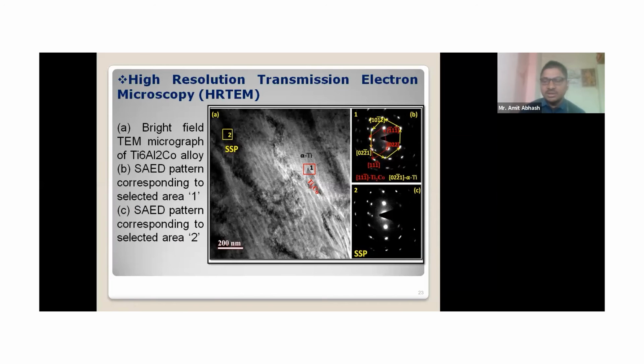So by going through the transmission HRTEM image, this is the bright field transmission electron micrograph of this one, and this is the SAED pattern, the corresponding SAED pattern of this phase. This here is the corresponding one, and this is alpha titanium, and another is Ti2Co. Again, by using the d values, we can just draw this one. And this is a different part, the solid solution part, and this is the SAED pattern of the solid solution part. So we can confirm it by going through the HRTEM image.